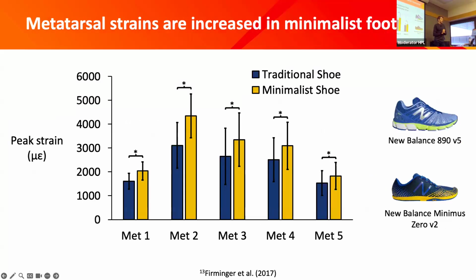In my master's degree, I looked at something similar to this, metatarsal strains in minimalist footwear, and I was looking at how much strain that bone was under. In the graph here, we're looking at the peak strain on the metatarsal bones. We have all 5 of the metatarsals here, and the yellow plots are the minimalist shoe, and the blue plots are the traditional shoe. Our minimalist shoe here has very little cushioning; it's very flexible.